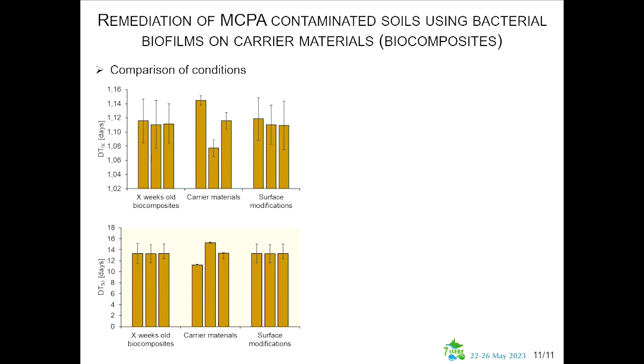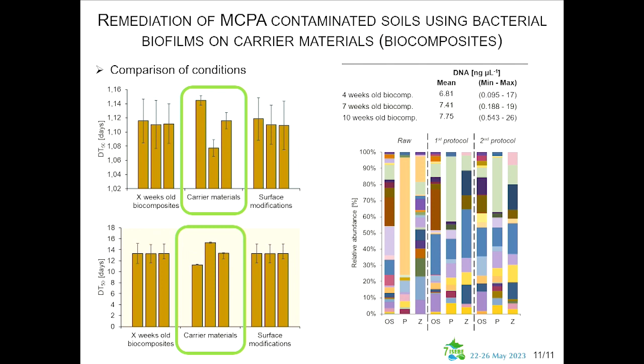So I looked at all the DT50 and tried to compare them according to these conditions. And what we can see is that only the carrier material really changes the dissipation behavior. So that's it. And I tried to look, for the 10 weeks old biocomposites, at what microbial communities are present. So I made TRFLP and only compared the different aspects of the microbial communities, and we can see differences. Here you have results for, at each time, oyster shell, pozzolana, and zeolites for raw materials, and after the different